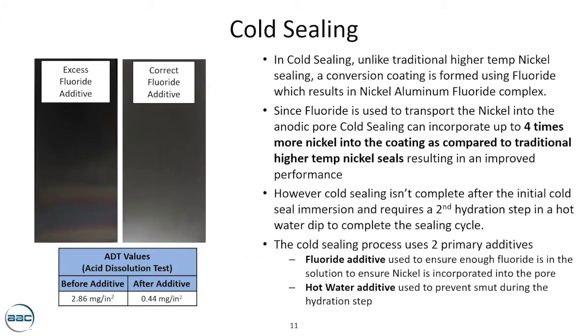Now, because of that, there is a second step associated with cold sealing, and it is a hydration step. And that hydration step is essentially a hot DI or hot water dip, ranging from anywhere from 5 to 7 minutes. It depends on the type of part, the type of alloy, but it's a dip of at least 5 minutes.